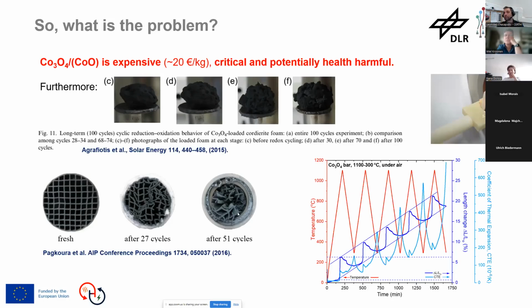Here you see it in a dilatometry experiment. The red line is the cycling between 300 and 1100, and the blue one here is the residual length. You see that the material is heated thermally and thermochemically, but then upon cooling, it does not return to its original dimension, but it's essentially longer, right? And this augmentation of the length is continuing until you have this effect that you see there.